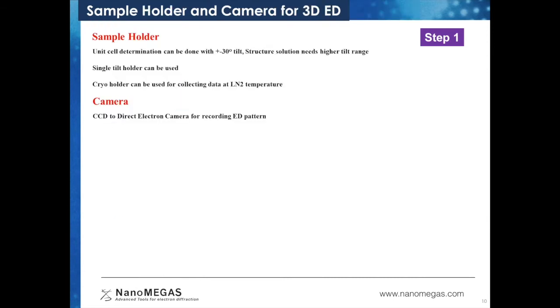Now, for the sample holder, one can use a single tilt holder. One can also use a cryo holder, especially if someone is working with beam sensitive materials. For unit cell determination, a smaller tilt range of plus minus 30 degrees is good enough to obtain reliable results. But for structure solution, a much higher tilt range is required. The required tilt range usually depends on the symmetry of the crystal.